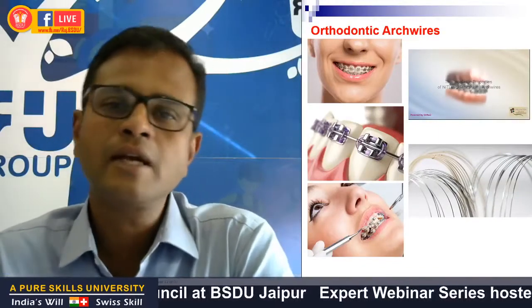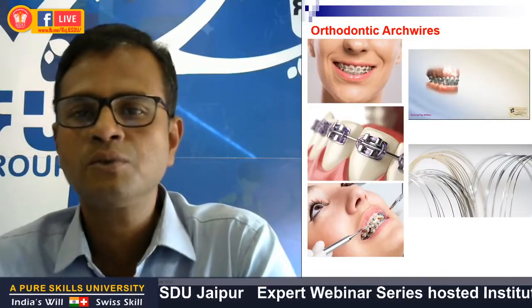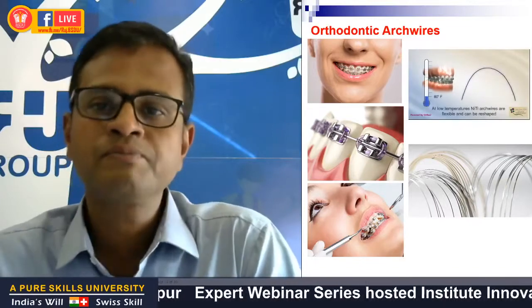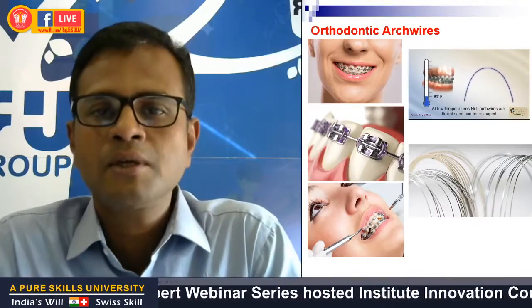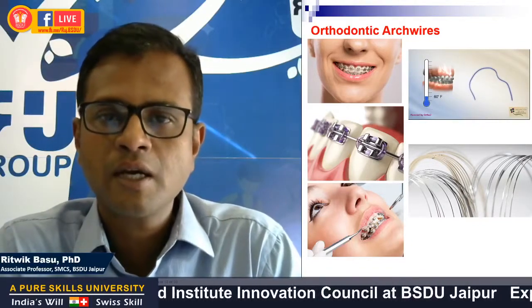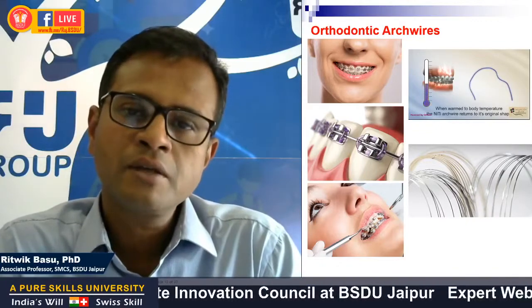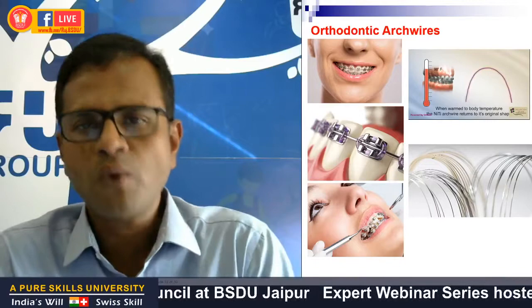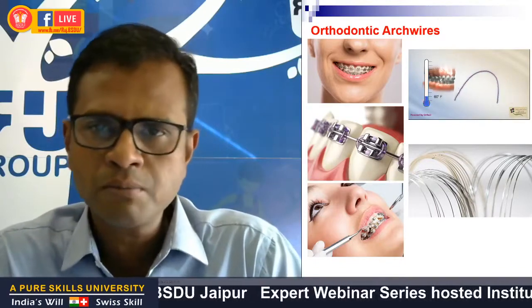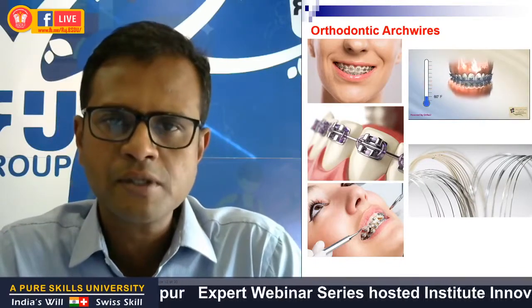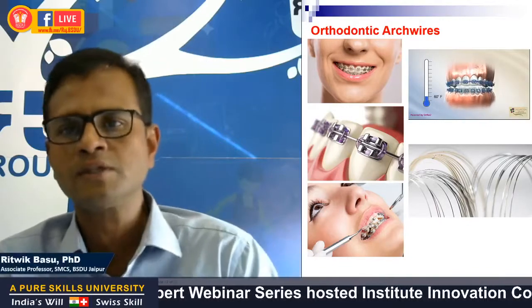So the nice thing about these wires is that at low temperatures, these wires exhibit a phase that is highly deformable. So you can twist it, turn it, give it any shape. While at high temperatures, typically when these wires come in contact with the body, it undergoes a phase transformation, and together with that is a shape change which is associated. So these wires are actually trained to go to a particular shape at high temperatures, and this is what we call as a training in shape memory alloys.